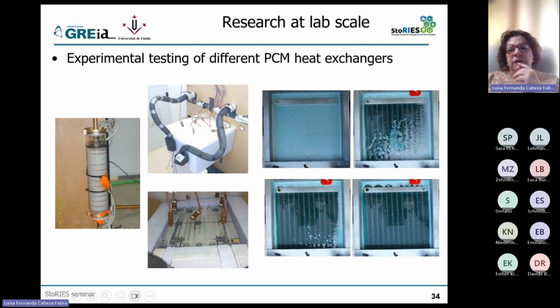And for us, it's very important to do this because the behavior of the different materials is very different. It's very different if you work with an organic material than if you work with an inorganic material, which would be a salt hydrate or a salt. And then here we test different designs of our heat exchangers. As I said, these are all shell and tube, but we have tested other ones. For example, here we were testing different fins to see how the system behaves and if we can improve this charging and discharging power, because in some applications we need it.